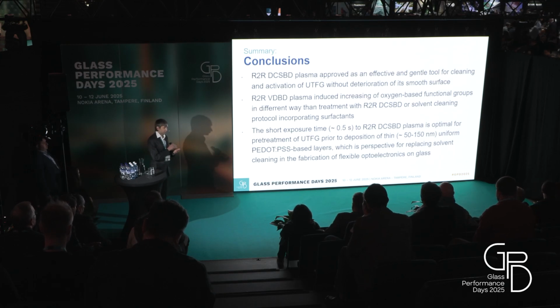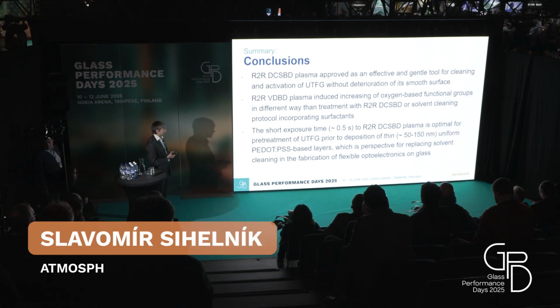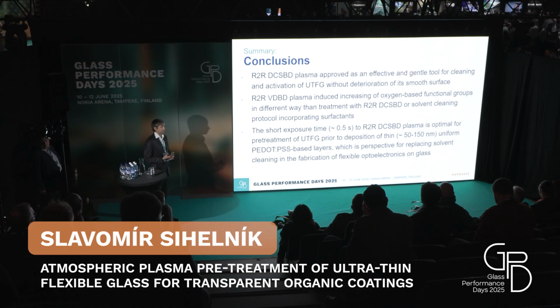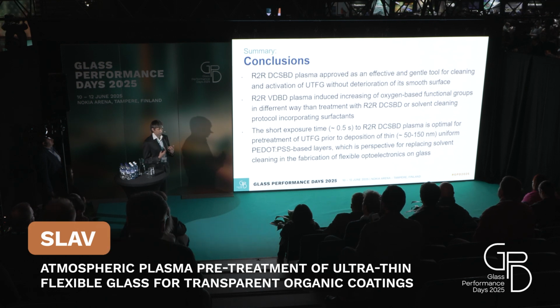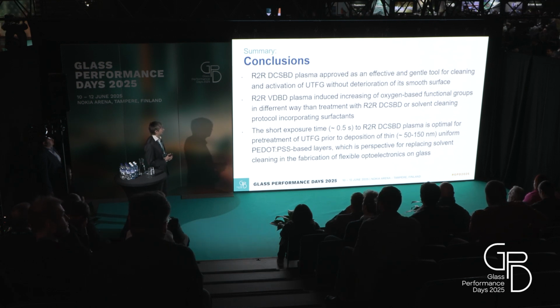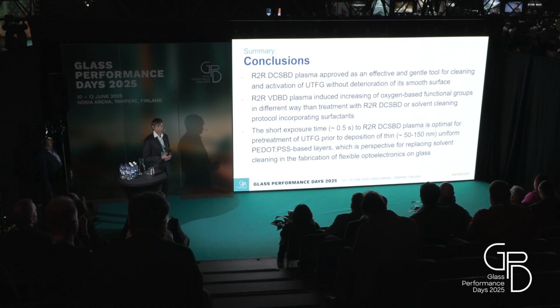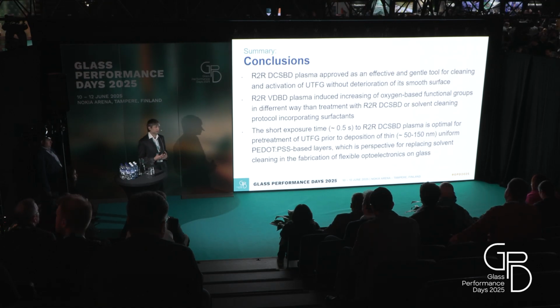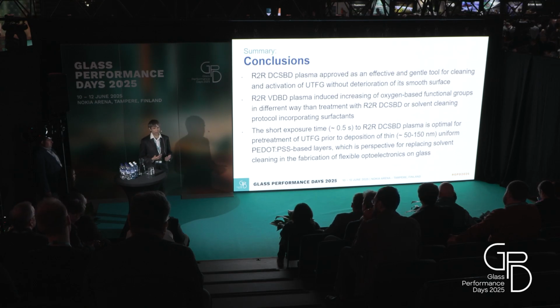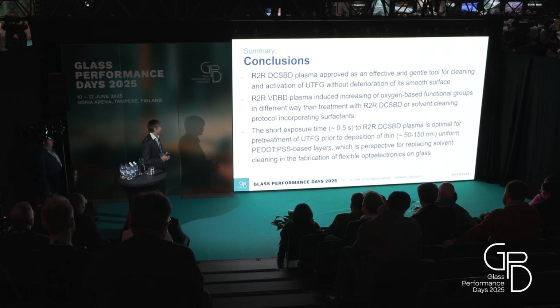The process acts only on the surface, and it increases the oxygen-based functional groups. But it works in a different way, which is due to the character of the plasma. So a good plasma source needs to be selected for the treatment if you want to incorporate it in this technology. The advantage of these atmospheric pressure plasma systems is that they are implementable in roll-to-roll processing, which flexible glass is suitable for. And we can replace the solvent cleaning protocol, which is also very interesting for the fabrication of flexible electronics.